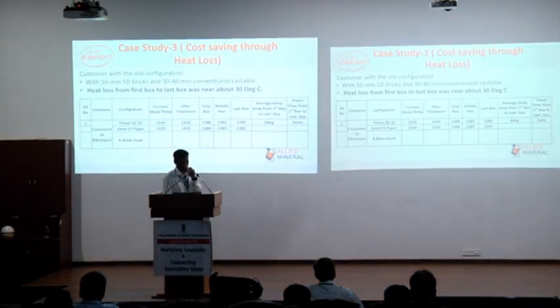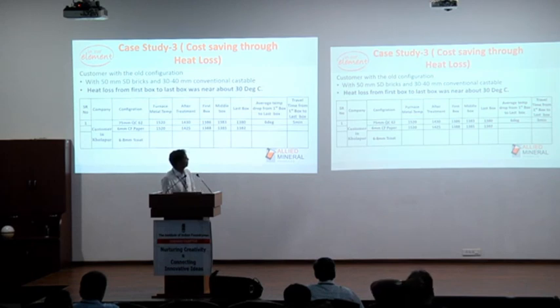So this is a case study, cost saving through heat loss. The traditional old configuration of the customer was 50 mm SD bricks, that is super duty bricks, and 30 to 40 mm of conventional castable. They had a heat loss of about 30 degrees from the first box to the last box. We modified the configuration with 6 mm ceramic paper, 75 mm of 62, which is a mullite-based castable, and 6 to 8 mm of T-coat, a magnesia-based coating material. We were able to achieve 6 degrees heat loss from the first box to the last box, and the travel time was almost 5 minutes.